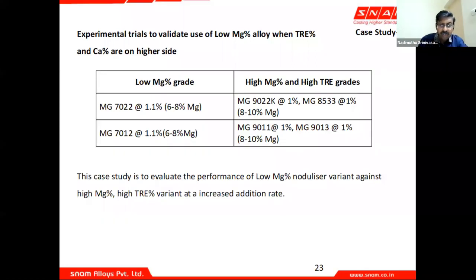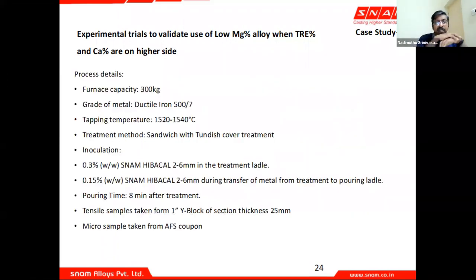So against these two, we thought, how can we reduce some amount of magnesium, slightly increase the rare earth and the calcium, and see how it performs. So we added at 1.1%, so that we see that there's not much difference in the magnesium losses. We used a furnace capacity of 300 kg, and this experiment was conducted on a ductile iron 500/7 grade. The tapping temperature is a normal tapping temperature that we have seen generally followed here, 1532 or so. And the treatment method we used was a sandwich with tundish, and the inoculant we used was a 0.3% high potency barium, calcium, aluminum inoculant.